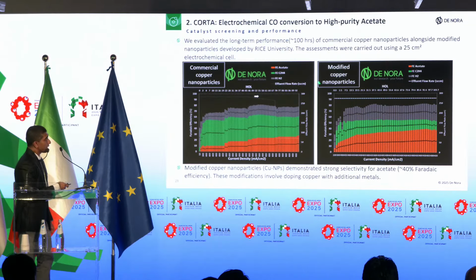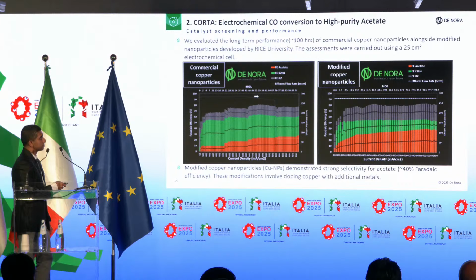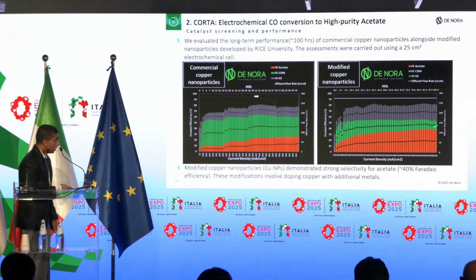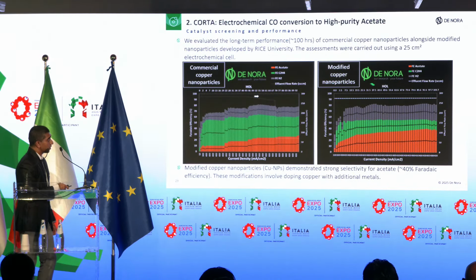Clearly, when we modify these copper nanoparticles, which means our partners dope copper with elements like palladium or silver to improve the selectivity of acetate, as you can see, we can increase the Faraday efficiency for acetate, and that means a decrease in the ethylene Faraday efficiency while maintaining the Faraday efficiency for hydrogen. Our goal in the next step is to further engineer the catalyst such that we can further increase the selectivity for acetate.